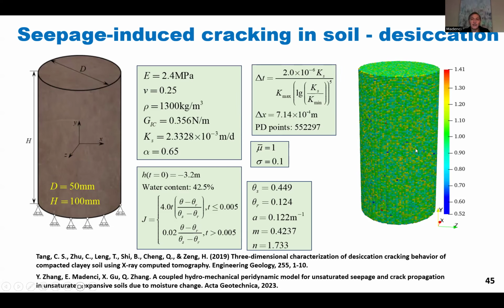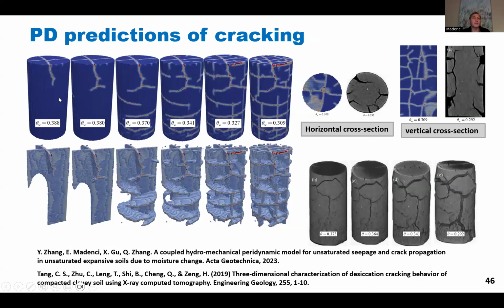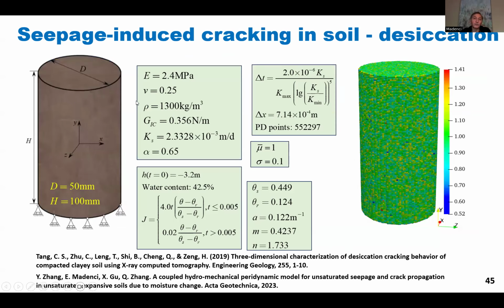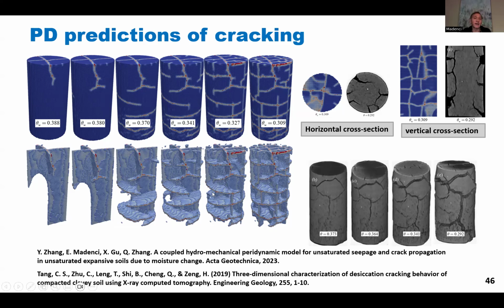So here you see these different colors in the discretization. Because we don't know where the crack is going to initiate, we added some randomness to the material properties and to the critical value that we use for bond breakage. And here you see the peridynamic predictions. That's the horizontal cross-section of the specimen, and this is the vertical cross-section. As you can see, other than the randomness, we don't fine-tune anything, we don't change anything, everything remains the same. And very nicely, it captures the crack growth patterns and how the crack initiates and propagates. Very complex.